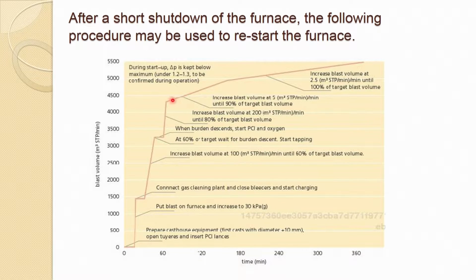And after that, you increase slowly the blast volume with 5 meter cube per minute until 90% of target you reach in sort of 2.5 hours, and then you increase the blast volume very slowly after that, at 2.5 meter cube per minute, until the 100% target is reached on the blast furnace. So, if you look at the minutes, it can take about 6 hours or so.